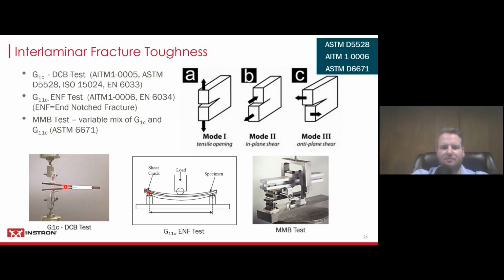The testing standard explains it, and then you start pulling this apart, and you need to determine the fracture toughness as the crack grows through the specimen this way. And then in the mode 2, it kind of looks like this. It's basically a 3-point bend setup, but you have a shear crack up here, and then try to grow it through. And then this is the mixed mode bending fixture. We kind of do both at the same time.